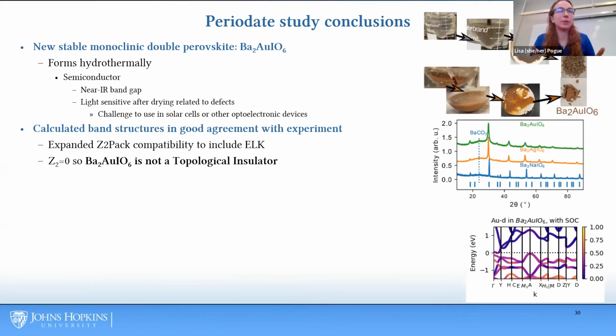From this study, I was able to conclude that there is a new barium gold periodate double perovskite that forms hydrothermally. It is a semiconductor with a near IR band gap, which is kind of unusual for the class of materials. It is light sensitive after drying, and this seems related to defects that can be traced to the hydrothermal synthesis process. This would also make it difficult to use in solar cells and other optoelectronic applications, and difficult to use in quantum information systems because that would tend to create decoherence. I was able to calculate the band structures of these materials and have good agreement with experiments, and was able to expand Z2Pack to work with ELK, an all-electron DFT code.